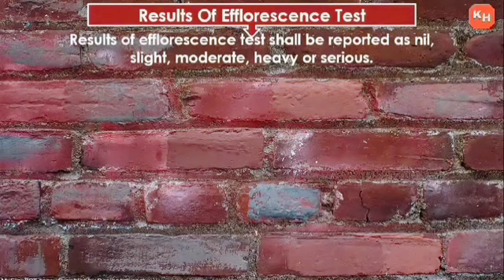Nil. If there is no noticeable deposit of efflorescence. Slight. When less than 10% of the exposed area of the brick is covered by a thin layer of salt. Moderate. When there is a heavier deposit than under slight, covering up to 50% of the exposed area of the brick surface, but unaccompanied by powdering or flaking of the surface.